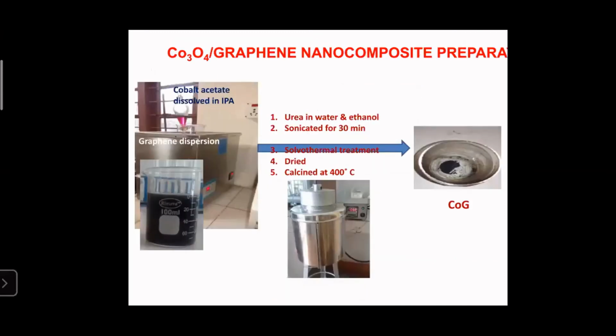And to this, for the formation of cobalt oxide graphene nanocomposite, we add cobalt acetate dissolved in IPA. And during solvothermal treatment, for the precipitation of cobalt oxide, we use urea. After solvothermal treatment, the mixture is filtered, washed, dried, and calcined at 400 degrees Celsius. And we got cobalt oxide graphene nanocomposite. We can note that the calcination temperature is 400 degrees Celsius.